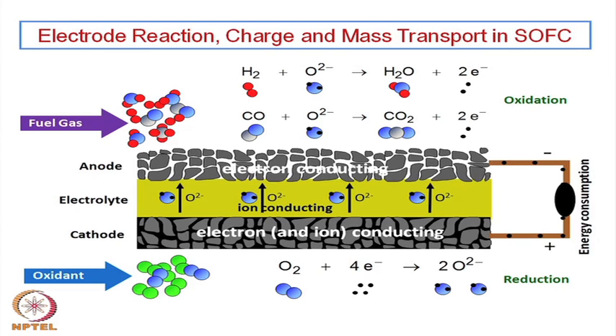many of the oxides in presence of hydrogen can reduce to their corresponding metal. So, one has to choose a particular electrolyte which should not be reduced even in presence of hydrogen. A reducing gas like hydrogen should not reduce it to the corresponding metal, and that is also at a higher temperature. Normally, many of the oxides will get reduced at a higher temperature in presence of hydrogen, but one has to choose an electrolyte in this case for the solid oxide fuel cell to be successful or operating.